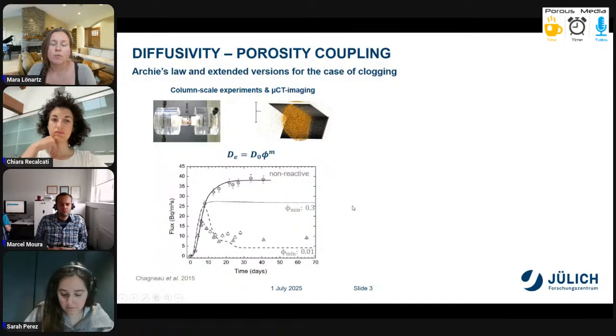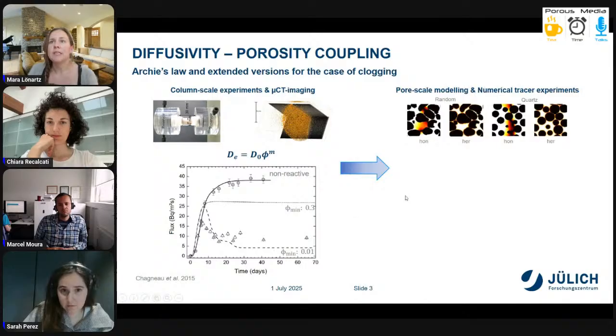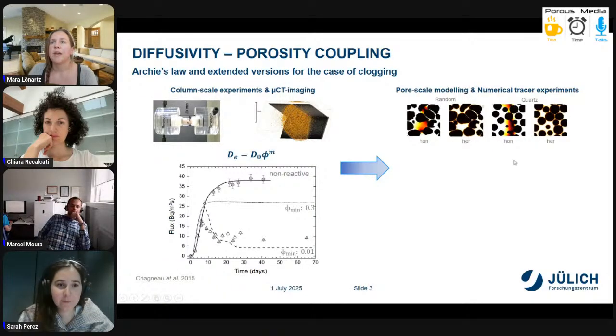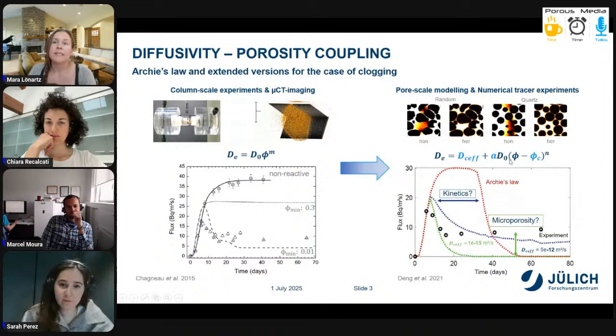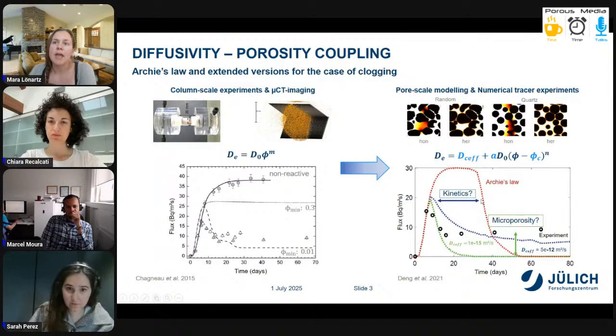A more recent idea was proposed by Deng et al. She conducted two-dimensional pore scale studies, considering different initial pore geometries and different nucleation and crystal growth scenarios. For the homogeneous case, she modeled the formation of a pattern on a precipitation front, and in the case of heterogeneous nucleation, we can see growth on the initial sand. Based on those experiments, she proposed an extended version of Archie's law, considering a critical effective diffusivity and critical porosity, and adding an additional fitting parameter. However, the results were still not captured by the model, and the critical effective diffusivity was simply estimated.